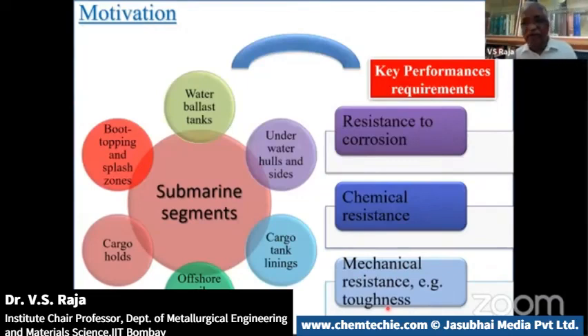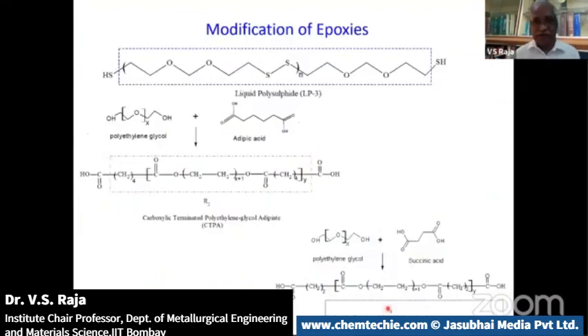So how do you really modify this? The epoxy has very strong cross-linking, right? When you have more cross-linking, it's very rigid, no doubt about it. It's not tough. So how to do that? You just get into the fundamental aspect of it. We borrowed something from the aerospace industry where people use polysulfide, right? Linear chain polysulfide is used. It's an elastomer, for example. It is used as a gasket and so on. So can we incorporate this polysulfide into the epoxy?